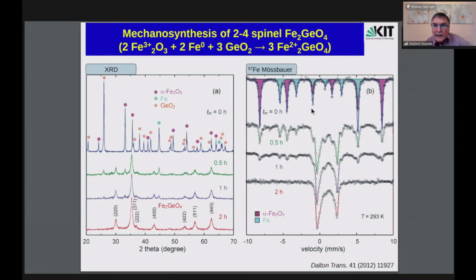On the right-hand side, you see the progress of mechanosynthesis followed by iron-57 Mössbauer spectroscopy. As you know, this method sees only iron-containing compounds, that means only hematite and metallic iron. With prolongation of milling time, you see the disappearance of the sextets corresponding to both adducts. After 2 hours of milling, there is a spectrum typical for ferrous iron in iron germanate.